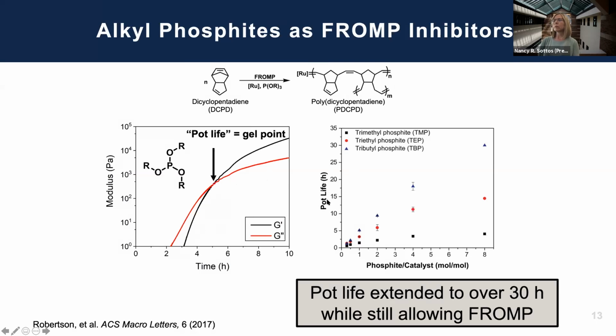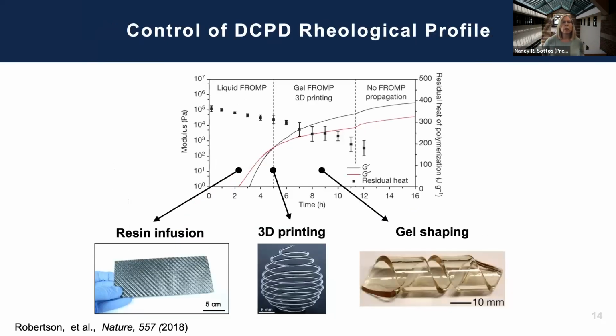And the amount of this phosphite inhibitor lets us tune where this gel point occurs. And so we can look at a plot of this pot life or gel point as a function of the inhibitor and catalyst concentrations. And what we found is that with these inhibitors, we're able to get over 30 hours of pot life in some systems, which enables us to do larger molds and structures. And as you'll see as I go through the talk, it enables a lot of different things. The other thing that we discovered in this system is that with the use of these inhibitors, we have a lot of control over the rheological profile. And that control over the rheology really enables high fidelity in our manufacturing processes as well.